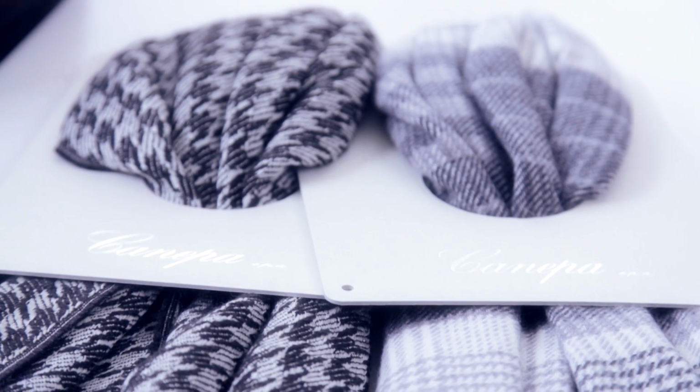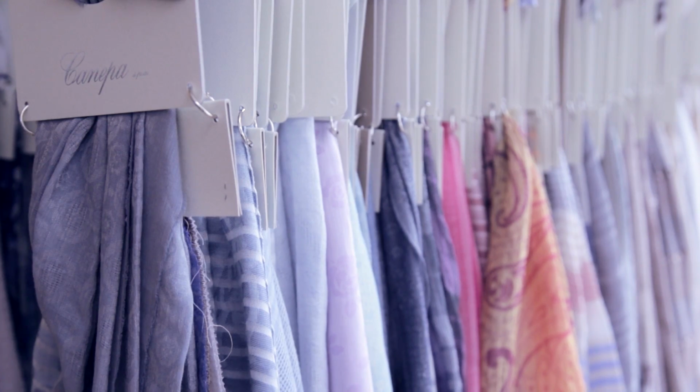It gives us technicians a great deal of satisfaction because we realized in the laboratory that this procedure is a process which we now define as permanent. We completed over 40 cycles in the washing machine, thus over 40 wash cycles. There is absolutely no difference in weight from beginning to end, thus from our perspective, what was there at the beginning is also there at the end. So all the prerogatives of sanitizing agents, anti-peeling agents, performing agents on the dimensional stability of fabric are never altered by usage, but are constant in time throughout the use of the product.